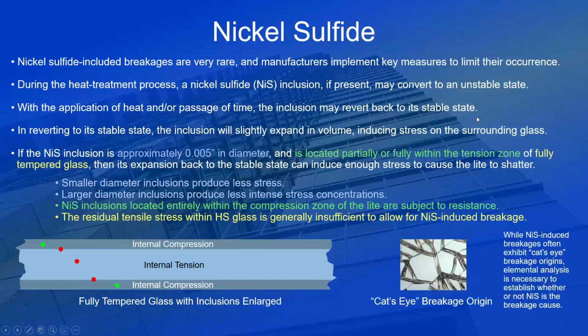Sorry, trouble with my mouse cursor. If that inclusion is in the perimeter of the IGU, meaning it's on the surface of the light, in the compression area, there's a lower risk of breakage. If that inclusion is in the middle of the light, in the tension area, there's a higher risk of breakage. You can see what a breakage pattern looks like there on the bottom right. Now, that cat's eye pattern does not necessarily mean that nickel sulfide is what caused the breakage.